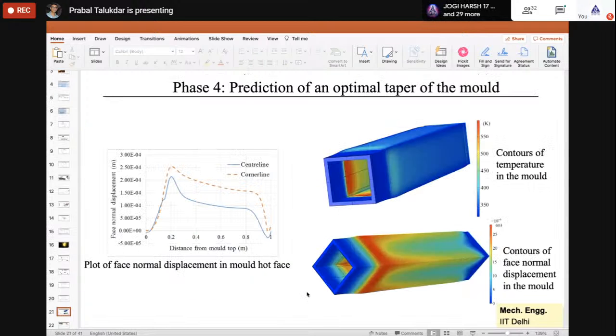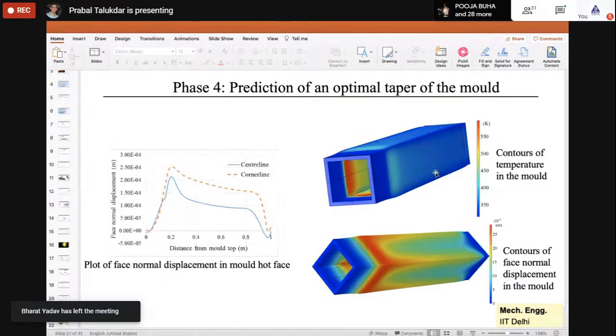There are some results which I am showing here. These are the results for the mold. You can see here the inside of the mold is hot, right? Because the molten liquid is flowing through this mold. That is why you can see the red color is extremely hot, close to the meniscus. This line is the meniscus line, because meniscus means the surface from which the liquid level starts. So this is very hot and gradually it cools down, and outside is cold because there is water flowing outside the mold. But of course this part is a little hotter because this is at the top of the mold. The temperature outside is not very high, somewhere in the range of 400 to 450.